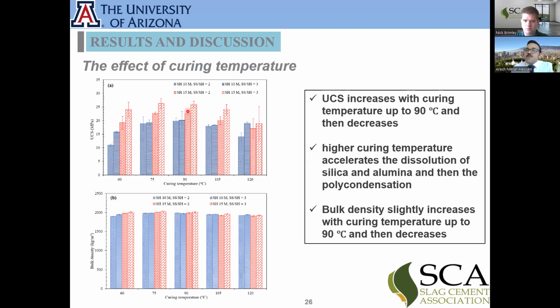With higher temperature, we are able to get more silica and alumina from the material. But as soon as we increase the temperature beyond a certain point, which here is 90 degrees Celsius, the water from the alkaline solution evaporates soon. And that causes two things. First, the geopolymer gel that quickly forms covers the other mine tailings, and since the water evaporates, we are not able to go deeper into the mine tailings and make the material release the silica and alumina. And second, as the water evaporates, more voids are created in the sample, which we are going to see at the microstructure level.